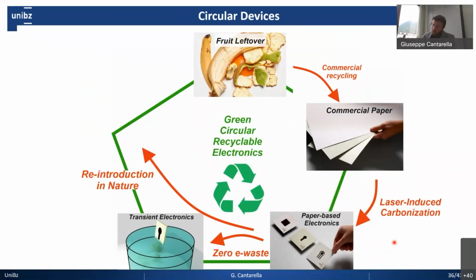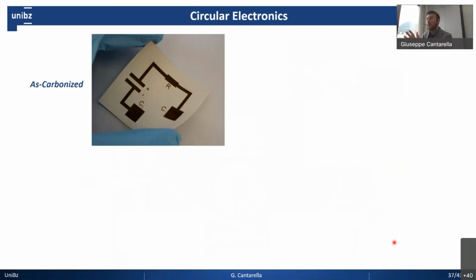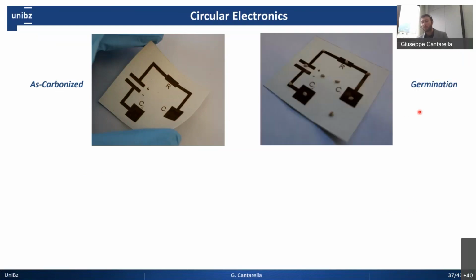So the second question, just to complete the circle, was, would it be possible to reintroduce the electronics, to throw it away in nature and see whether it could be functional? So what we did was a very simple experiment that I'm sure most of us have performed at least once during childhood, which consists in taking a specific substrate. In our case, it is a carbonized sample with a very simple RC circuit, so one resistance and two capacitors. And what we did is perform the so-called germination test, which means placing some natural seeds, these are tomato seeds, on top of the paper and on top of the carbonized part, to see whether our electronics can become a support to make the plants and the seeds grow.